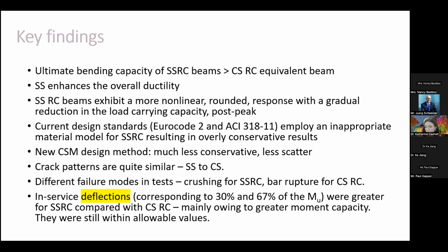For the set of tests we looked at, the failure mode was actually different. The stainless steel specimens tended to crush, the concrete crushed, whereas the bars ruptured in the carbon steel equivalent. So again, that's important for the ductility and the warning of failure. Deflections were a bit of an issue. The stainless steel members did deflect further as they progressed through the response, but not as much as we actually anticipated. Still well within the allowable values.